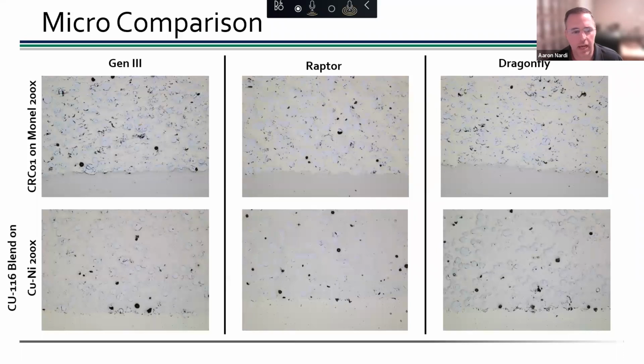Here's just a snapshot of the three systems with microstructures. So you see the Gen 3 to the left, Raptor in the middle, Dragonfly to the right. And then these are two different materials. One is a chrome carbide, nickel-based material, and then the other one is a copper nickel material.